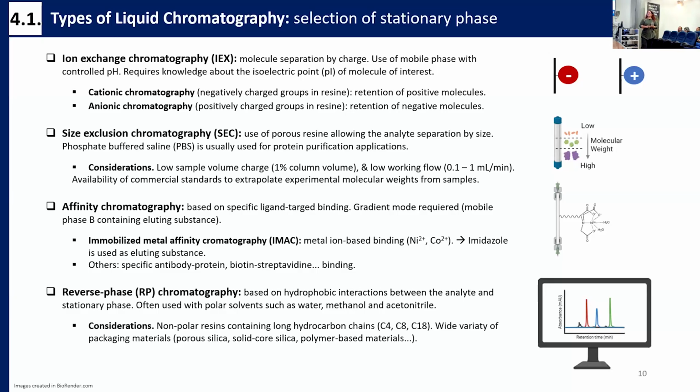also the characterization of the aggregation percentage of your samples, but it can also be used for release studies, where we can have the nanoparticle and the released drug. The released drug has a lower size, so it will be retained inside the pores of the silica, and then the nanoparticles with higher size will be eluted first.